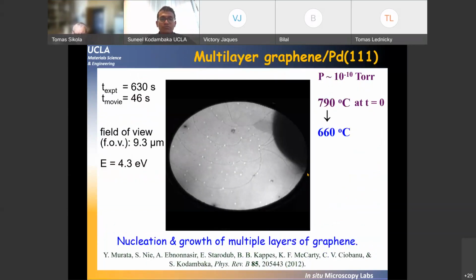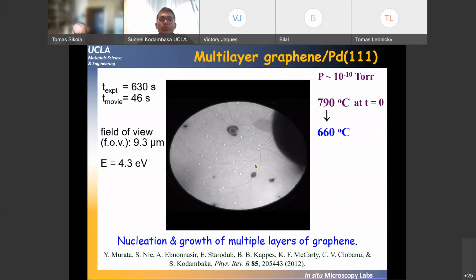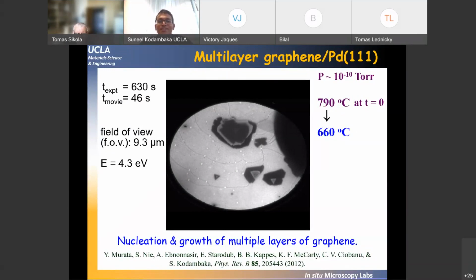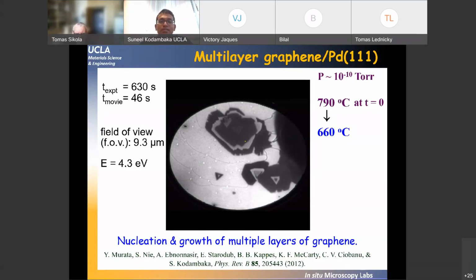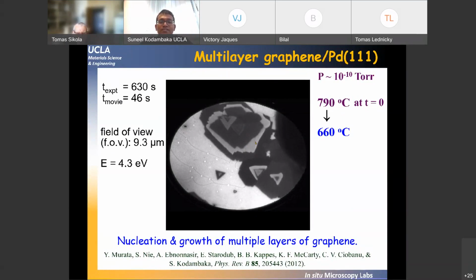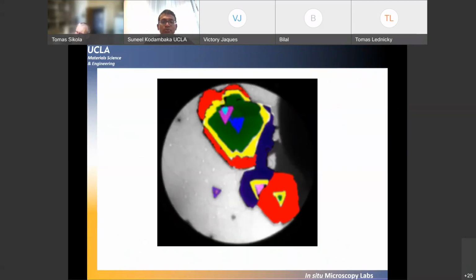Okay, and this is another experiment where instead of cooling it by a smaller delta T, if you cool it to more cooler temperatures, then you have more carbon segregating onto the surface. And so what you're looking at is multi-layer graphene islands growing, and you have this alternating contrast change between alternating layers of graphene. And here is a color-coded image to show you that you have multiple layers of graphene grow selectively, probably at some defect sites on the surface.